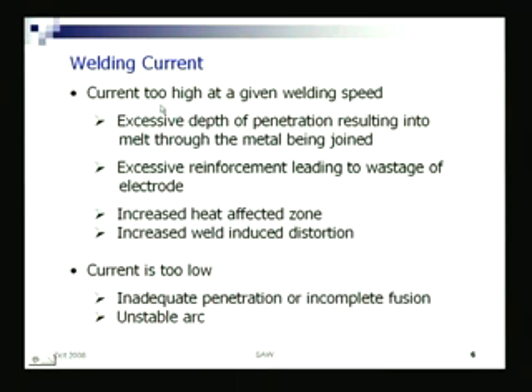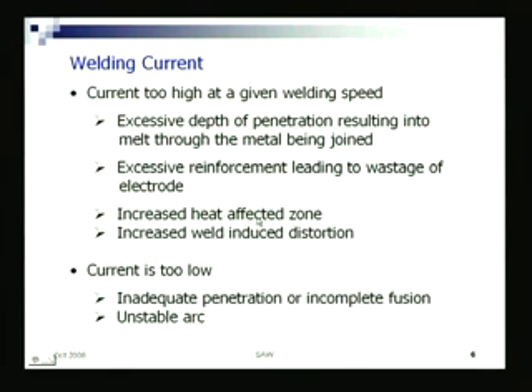What we are trying to show here is, current too high means, taking all other parameters remaining constant, if you increase the current too high, you will have effects like increased heat affected zone and increased weld distortion. Whereas if the current is too low, there will obviously be inadequate or incomplete fusion, and also an unstable arc, meaning the arc keeps going on and off.